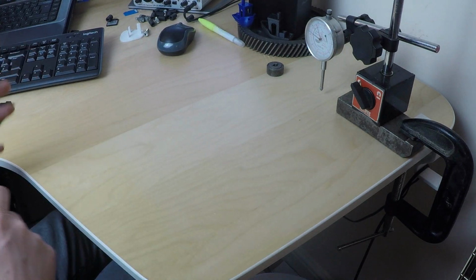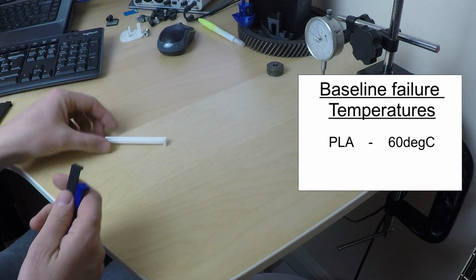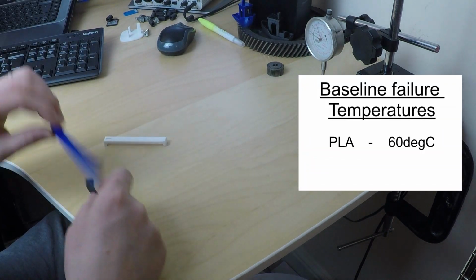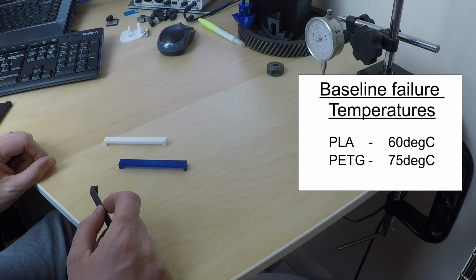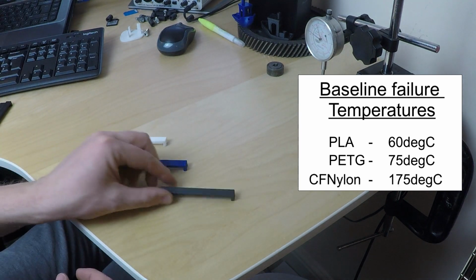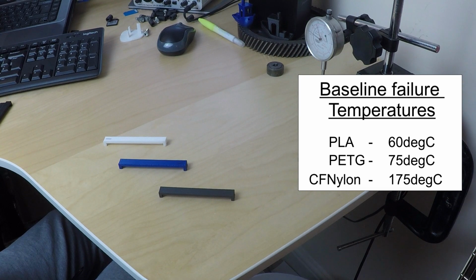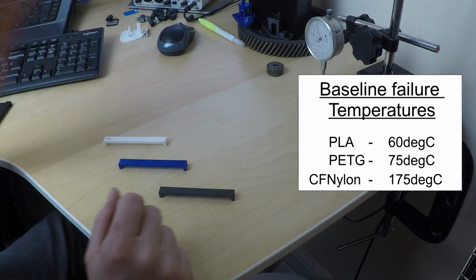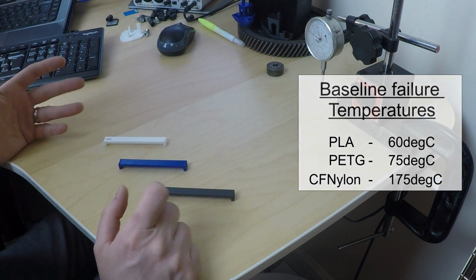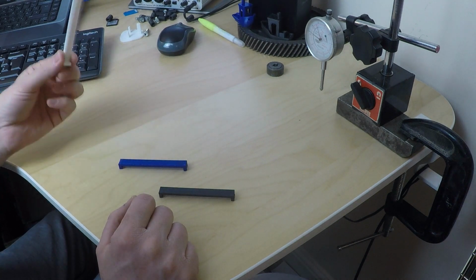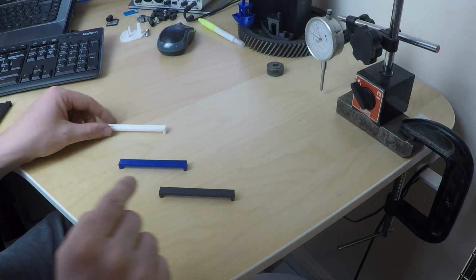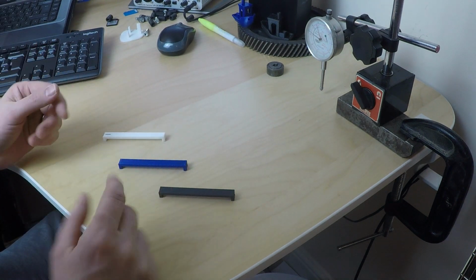So we have a baseline, and no surprise, the PLA gave up pretty early. The PETG was a little better as expected, but the carbon fibre nylon, wow, that's got some serious performance straight out the box. But as we know, PLA can be improved by annealing, but can we improve nylon and PETG?